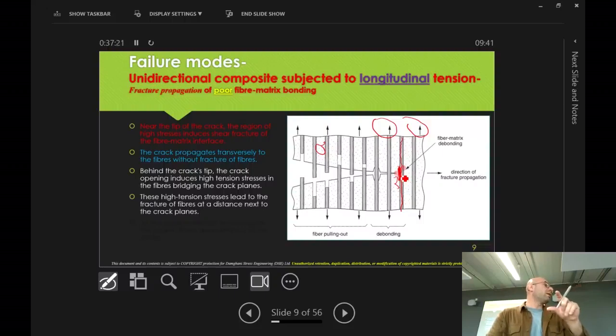So what does it have to do? It needs to redistribute the stresses. So instead of using that surface, it's got to use that surface here, that interface. Okay? So you have some stresses that used to go through this surface. They don't have any other surface. They have to redistribute, go through this surface and this surface. So these stresses go even higher at these surfaces.